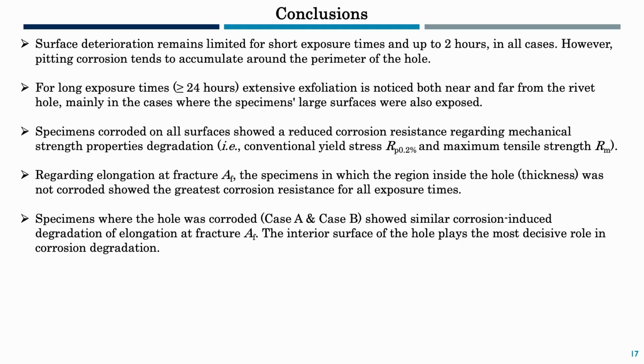and specimens corroded on all surfaces showed a reduced corrosion resistance regarding the mechanical strength properties, while specimens where the inside of the hole was also exposed to the EXCO solution showed higher corrosion degradation for all exposure times. And the interior surface of the hole was found to play the most decisive role in this corrosion degradation.